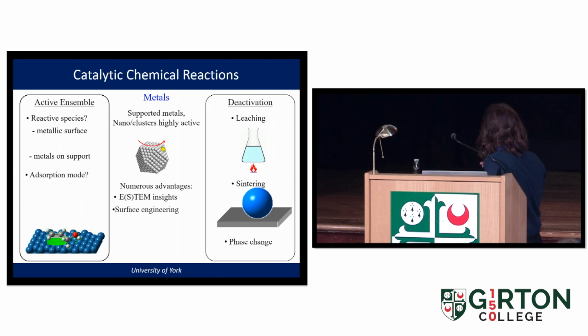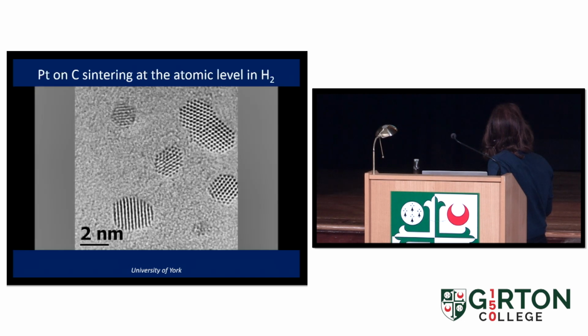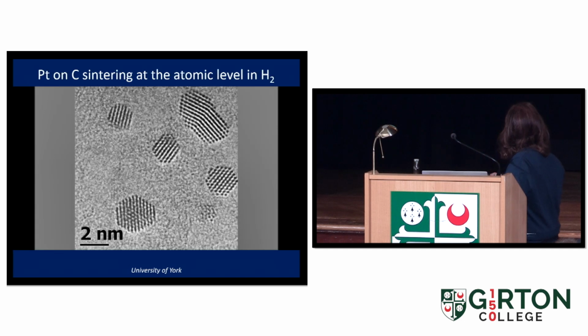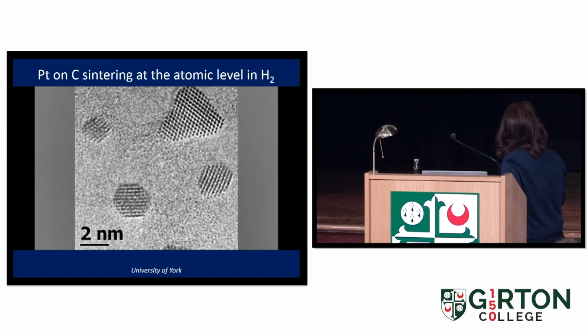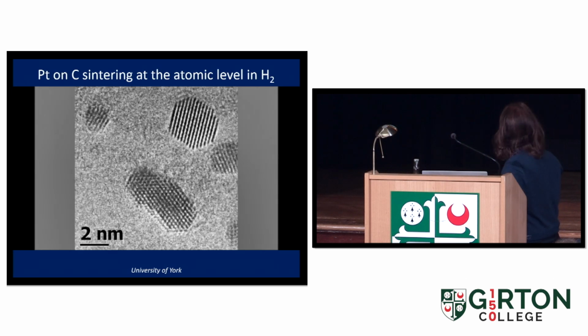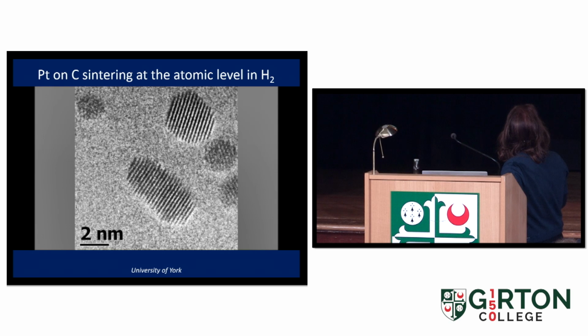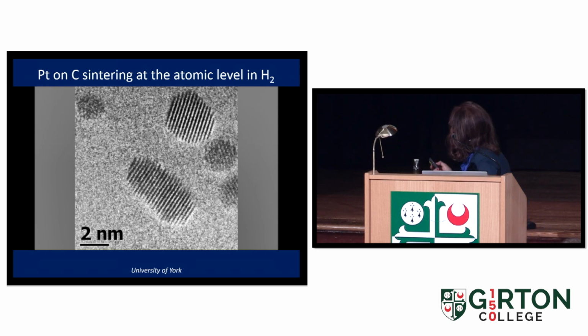So that's called sintering. For example, imagine all these single atoms become a clump, you will lose the surface area and the catalyst deactivates. So we need to understand all that. In the next video, in the real-time video, you'll see how the small particles like this become large particles. This is a platinum on carbon, and you can see very beautifully how this becomes large and sinter. And we need to understand that to optimize the process.